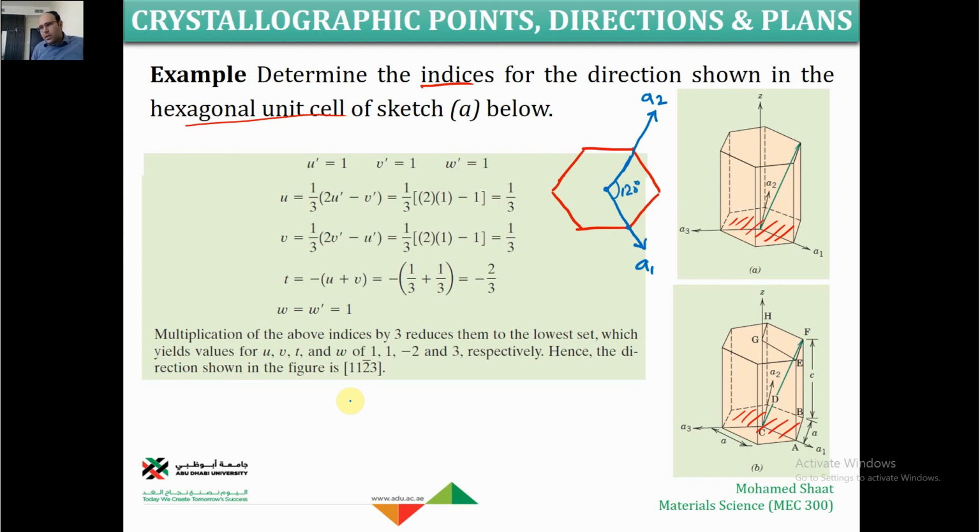It is not 90 degrees. Make sense? So your objective is just to define the A1 and A2 directions like X and Y. The distance you move parallel to A1 gives you U prime. The distance you move parallel to A2 gives you V prime. The distance you move vertically, parallel to Z, gives you W prime.